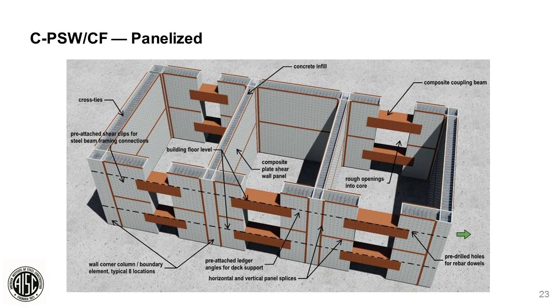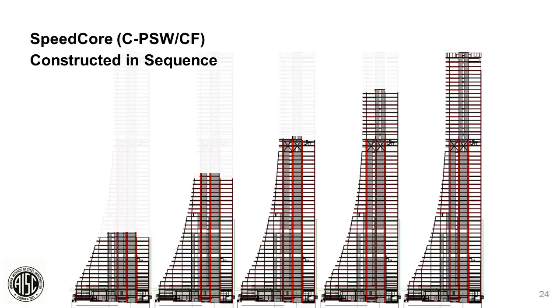And the last step of the process now is the concrete infill that you see here. And that is a trailing operation where you're pumping full the core as the core is being erected ahead of you. So you're several levels below the active erection deck, and you're filling the core roughly at the same time or just in advance of filling the composite deck floor slabs. So the concreting operation becomes a completely trailing operation.